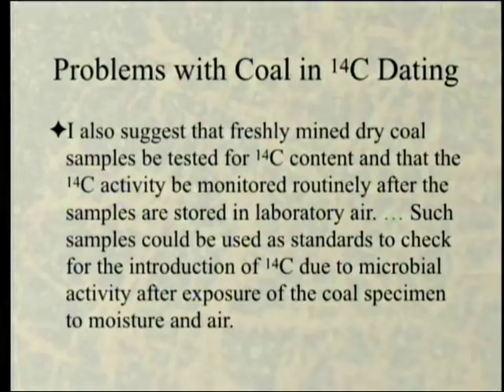I also suggest that freshly mined dry coal samples be tested for carbon-14 content, and that the carbon-14 activity be monitored routinely after the samples are stored in laboratory air. Yeah, can this work? Do a little experimenting. Yes. Such samples could be used as standards to check for the introduction of carbon-14 due to microbial activity after exposure of the coal specimen to moisture and air.